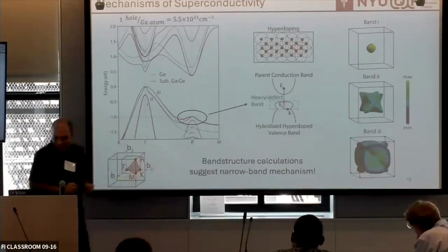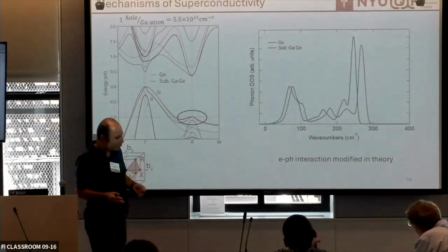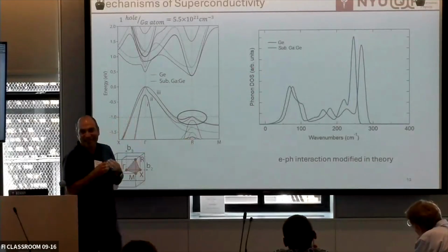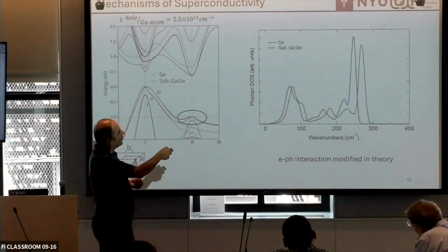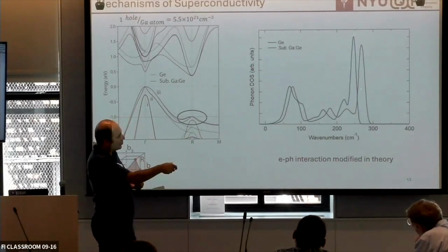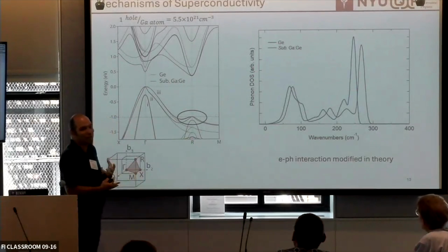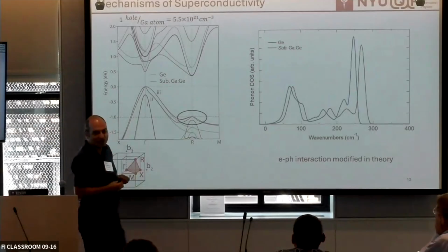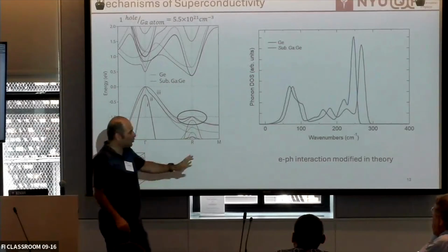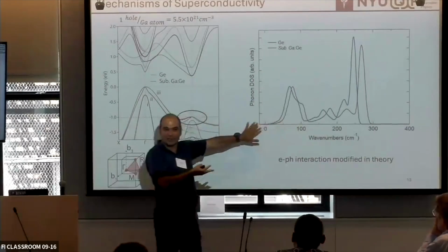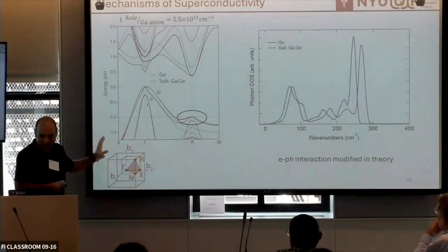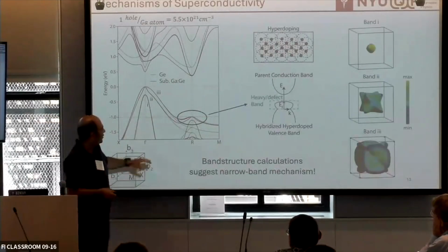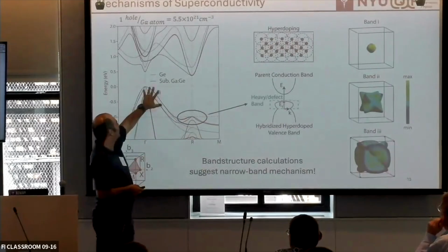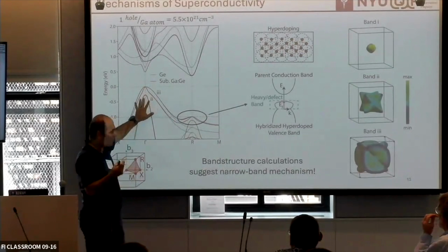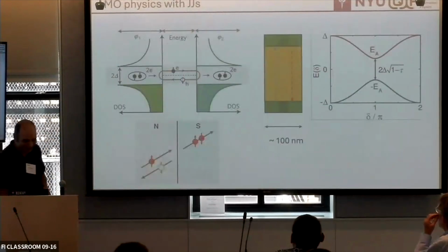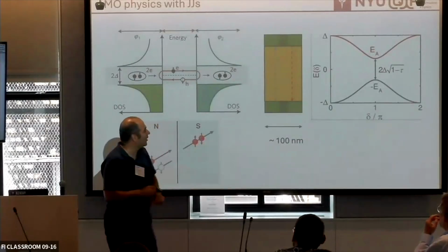That's one idea. We are not sure, but theoretically, if you also calculate the phonon density of states, there is a big, measurable difference between pure germanium and gallium germanium. If that's true, it means the electron-phonon coupling is also modified due to the strain and the distortion of the mass. Which one is true? We don't know. We do not see this in experiments that would target electron-phonon distortion, so we are still staying with the first one, the flat band. But it's hard to believe that a small pocket, because this is 1 meV, proximitizes a lot of electrons here. Somehow maybe it is possible. Eugene can help me with this. So that was a small discovery that we had.